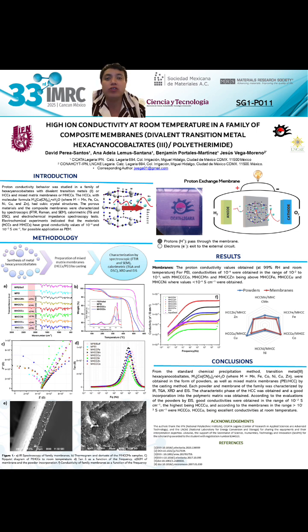According to the evaluation of the powders by impedance spectroscopy, good conductivities were obtained in the range of 10^-2 Siemens per centimeter, the highest being copper, and for the membranes in the range of 10^-3 Siemens per centimeter, the highest were cobalt and copper, being excellent conductivities at room temperature.